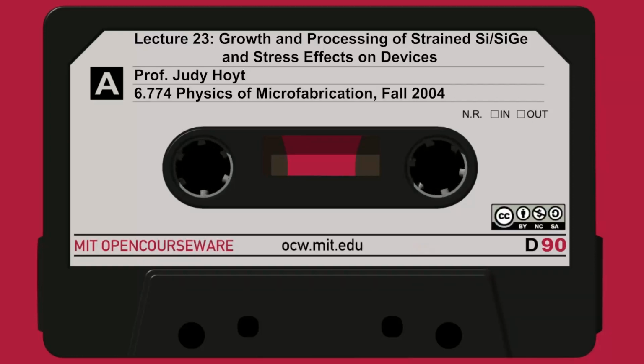So on slide 20, I'm just sort of reviewing for you, giving you an idea of some of the early measurements people made of how the mobility was enhanced. And the left side is for N MOSFETs. And you see this black dashed line is for control devices. And these other lines on top are for 10% germanium in the substrate, 20 and 30. You see, as you add more germanium in the substrate, the whole of the electron mobility curve moves up, and you get a nice enhancement.